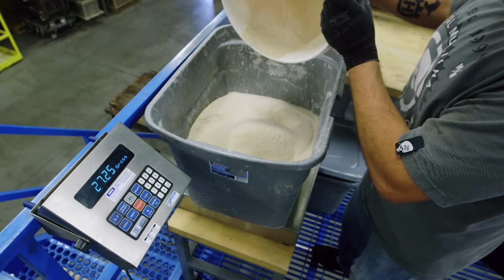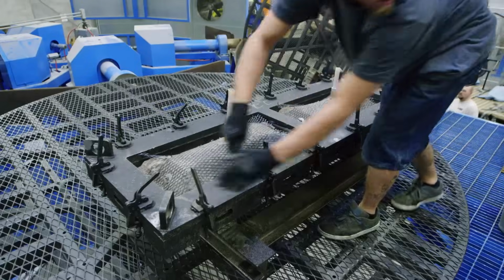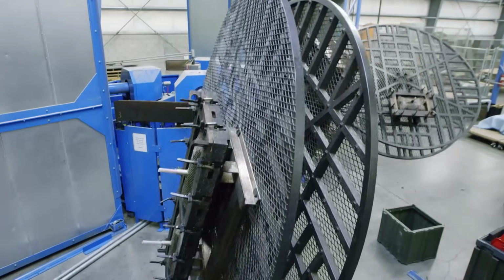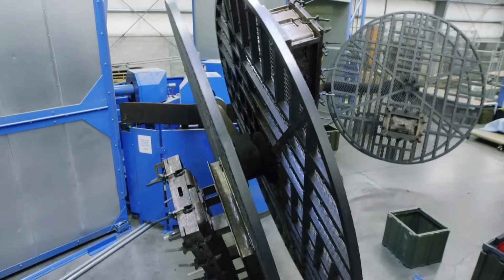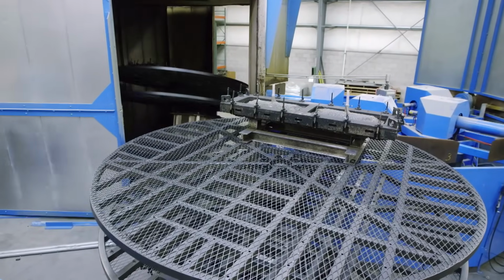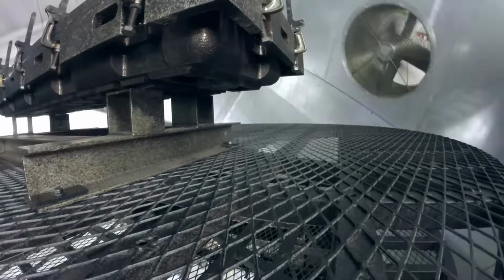Grains of sand-colored polyethylene are weighed out, then shoveled into a mold. Then a lid is put on, and it's secured to a robotic arm. First, the mold is rotated so the polyethylene grains inside are distributed evenly. Next, the arm moves into a large oven that heats the poly to 300 degrees Celsius for 20 minutes.